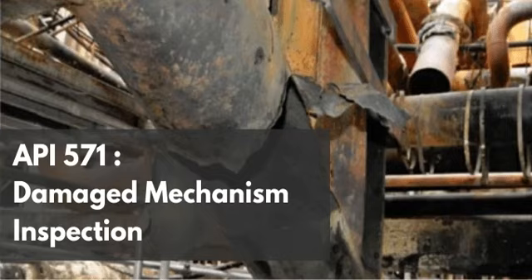Okay, 70 ksi. Let's talk about that. Yeah, the 70 ksi threshold is a hard dividing line in materials engineering for this mechanism. ksi stands for kilopounds per square inch. Right, so it's a measure of the steel's ultimate tensile strength. Exactly how much force it takes to physically pull the metal apart until it breaks. Standard piping grades, atmospheric storage tank plates, basic vessel materials, these often fall under that 70 ksi limit. Okay, so if you use these lower strength materials, you have an engineering out. You can apply a stress relief heat treatment to effectively neutralize the threat.